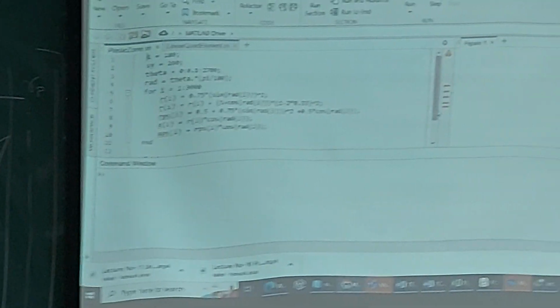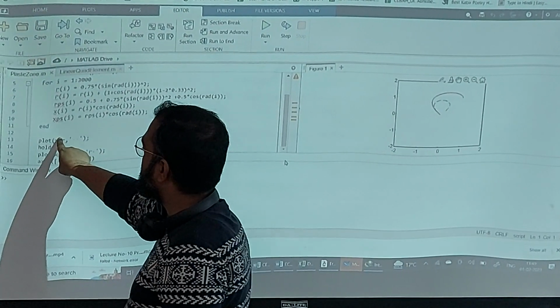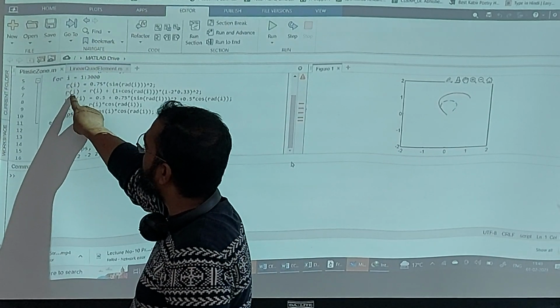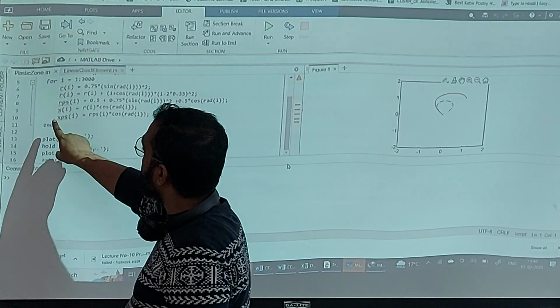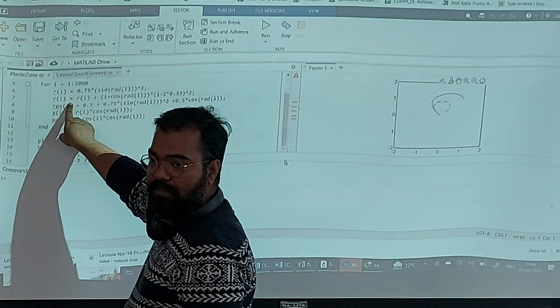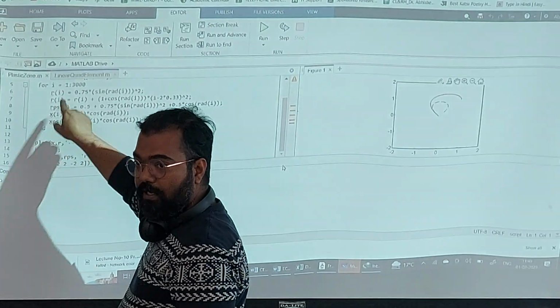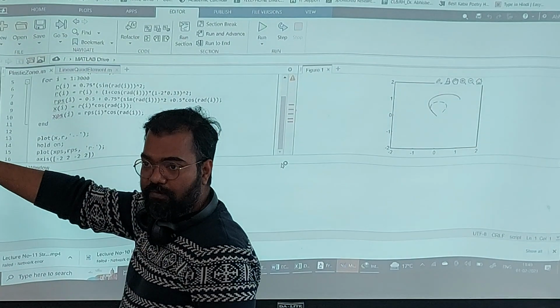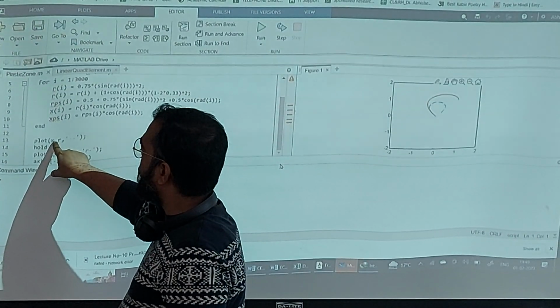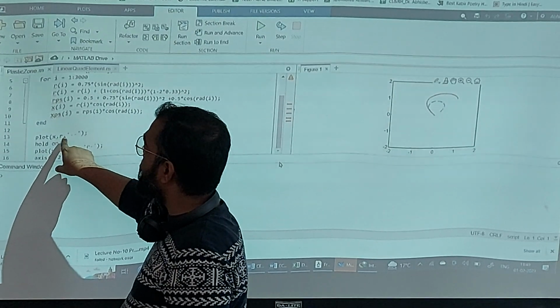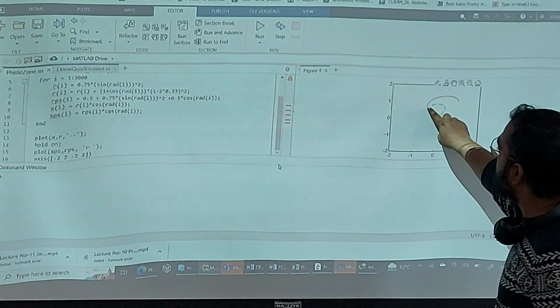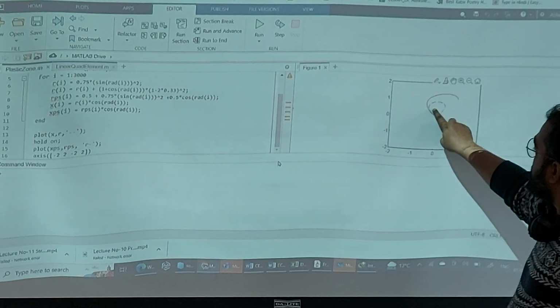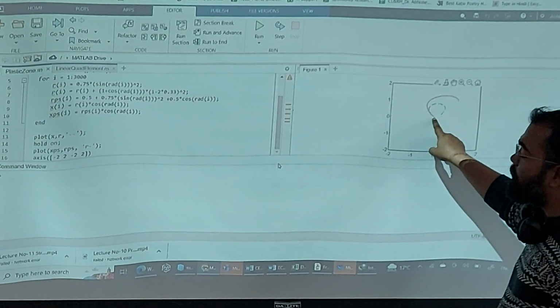And the red one, you might not believe me, so that's why I'm showing you that. So you see x and r. So r here is for plane strain, and rps is r for plane stress. You'll get two different expressions because sigma 3 will be different. So r for plane strain is plotted with a dashed line. This is the dashed line, and this is the tip of the graph.